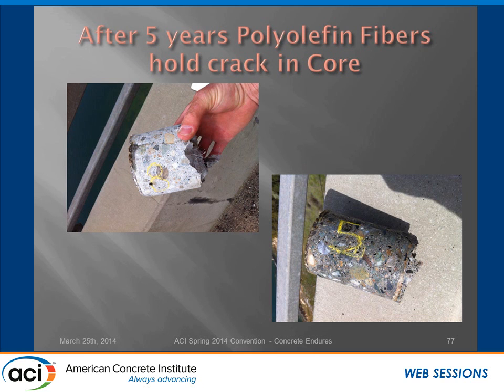5 years later, we came back and we were looking in the sections where we put the SRA and where we put the fibers and the SRA, and we're looking for cracks. Very hard to find cracks. And the bottom right is a core, just showing you, we thought we might get a crack there, but there was no cracks. And the top left is where we actually did find a crack.